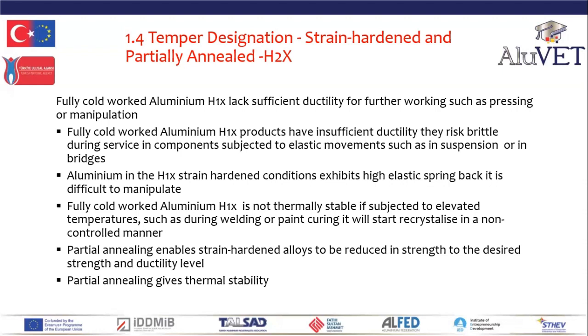Now, partial annealing enables strain-hardened alloys to be reduced in strength to the desired strength and ductility levels. Partial annealing gives thermal stability, preventing the aluminium recrystallizing in a non-controlled manner. Thus, on exposure for short periods to elevated temperatures, the annealed strength and ductility will not change.